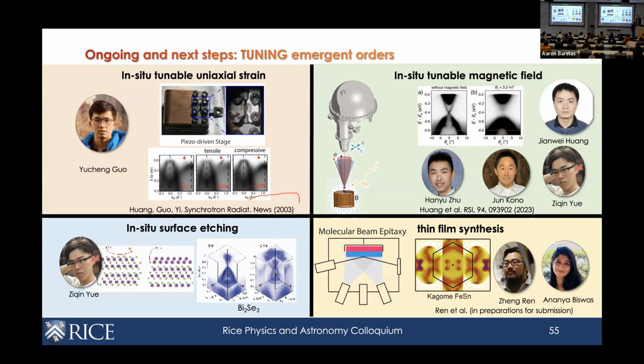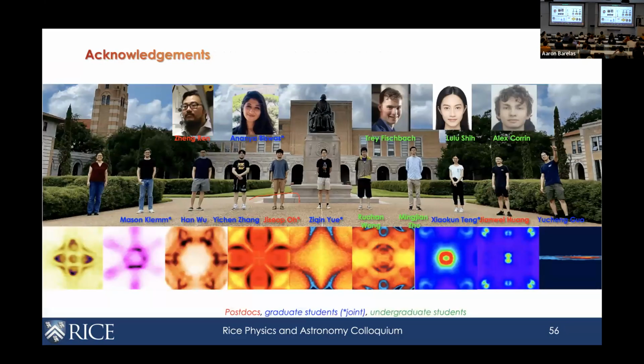And then this is an in situ tunable magnetic field that we're developing together with Han Yu's group and also with Jun's group. And this is a very, very exciting direction. We're now starting to see some evidence of direct field effect on band dispersions in these chiral materials. And then finally, this is the MBE system that our postdoc Zheng has set up. We're starting to grow some Kagome thin films. If anybody's interested in collaborating, we're very happy to talk about that.